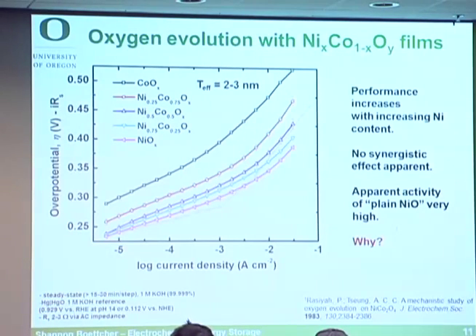And how you read this graph, this is called the Tafel plot. Again, this is the overpotential to drive the reaction at a given current density. This is on a log scale. So this is the rate of the reaction increasing here, and the driving force, the real electrochemical, thermodynamic driving force, on the y-axis. So good catalysts have points down here and bad up here. Okay, so nickel oxide was the best, cobalt oxide was the worst.